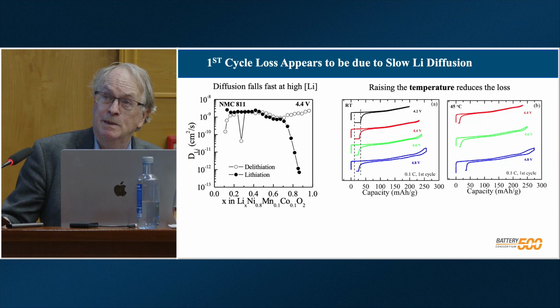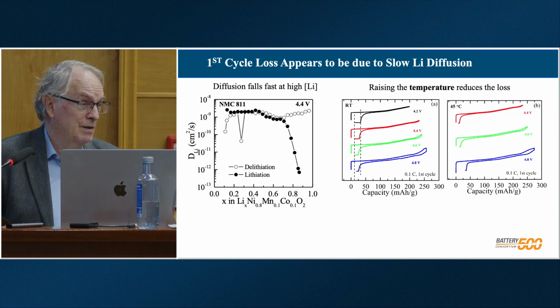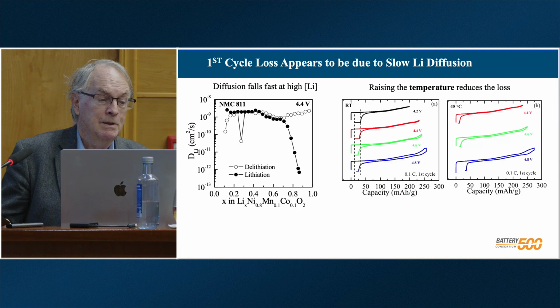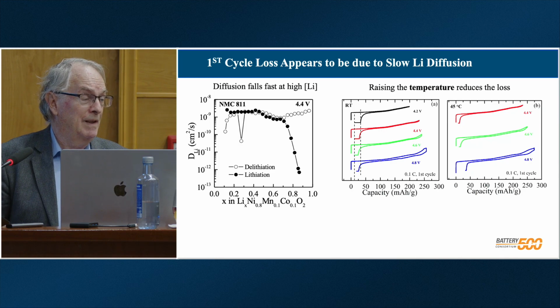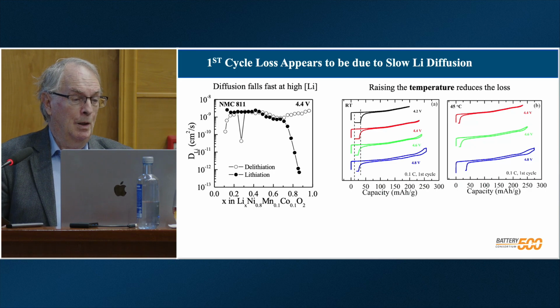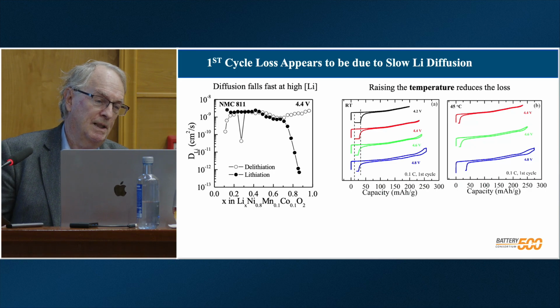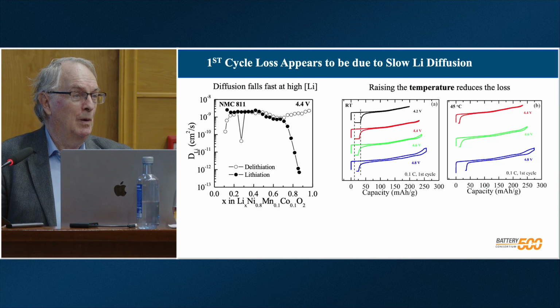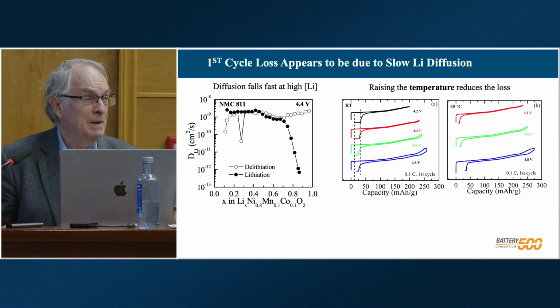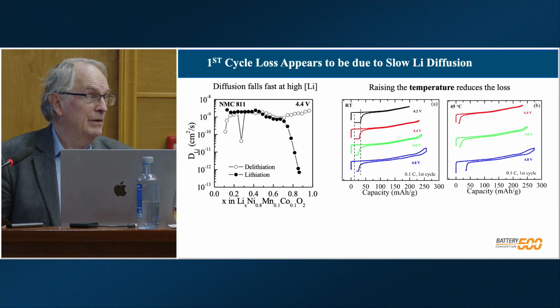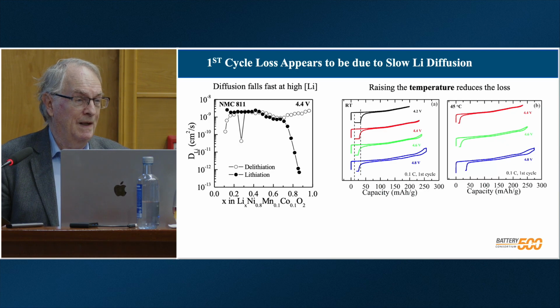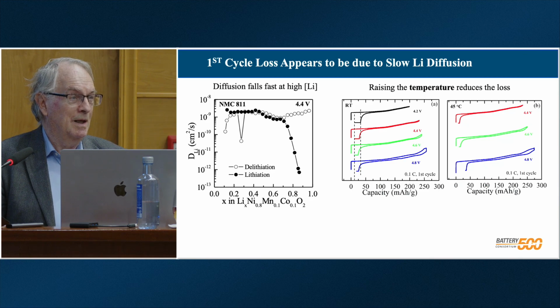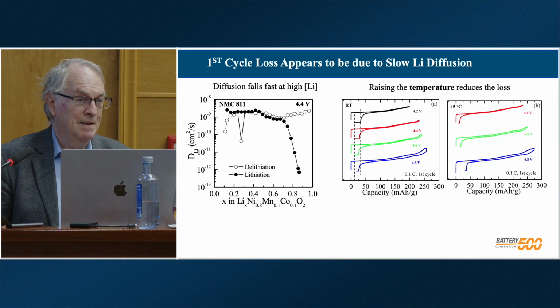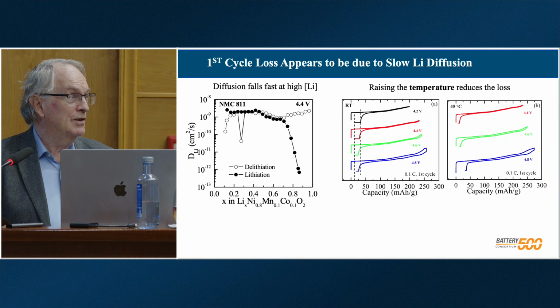And so what we did is measure the diffusion coefficient of the lithium in these materials. The solid circles is the diffusion coefficient of the lithium going into the materials, and the open circle is just the lithium coming out. And you can see we fall off a cliff at about 70% of the lithium in the material. This is due to the diffusion mechanism in these materials. It's a vacancy mechanism, and it turns out you need 2 vacancies next to each other for the lithium ion to diffuse very fast. The best way to understand that is just look around you.